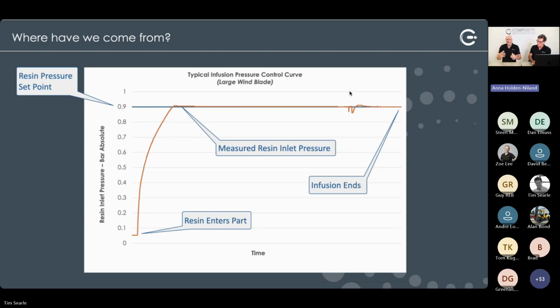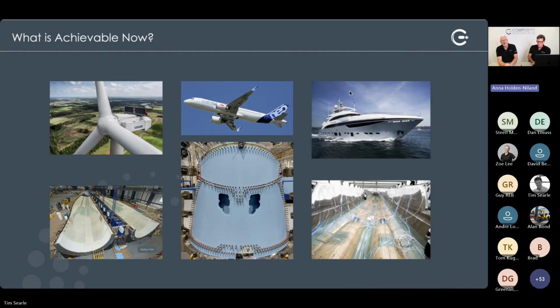These systems also compensate during process for events which occur on the fly as the part is being infused. For example, another resin inlet being opened or closed, which creates a pressure variation, or part permeability variations as we go from monolithic to cored sections, for example. So controlling these leads us to really true automation of the resin delivery into these complex parts. And although this graph is for a large wind turbine blade, the principles and requirements are exactly the same for a high quality, high VF aerospace carbon epoxy component.